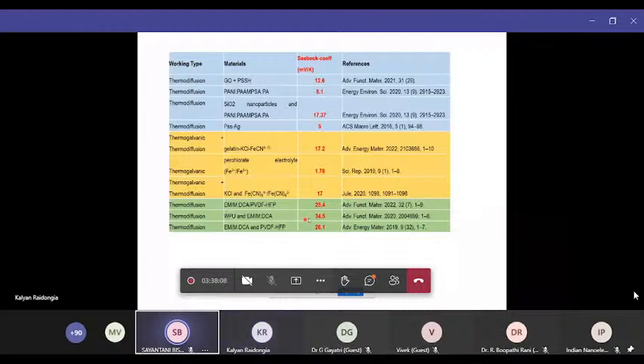It's a significant improvement, but there are problems: most of these polymeric materials have low ionic conductivity, lack long-term stability, and are not suitable for humid environments, and they are all based on organic polymer systems. So even thermal shock, anytime they come in contact with a high temperature, they get damaged. This is a problem for realistic application, because this material itself is targeted for harvesting energy from a temperature difference, but it cannot tolerate exposure to high temperature. So this was the issue.